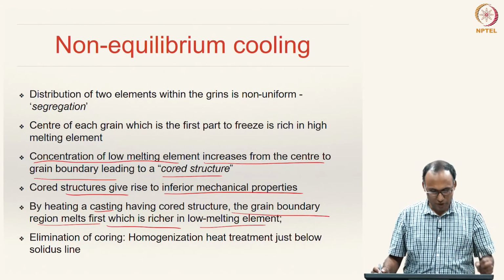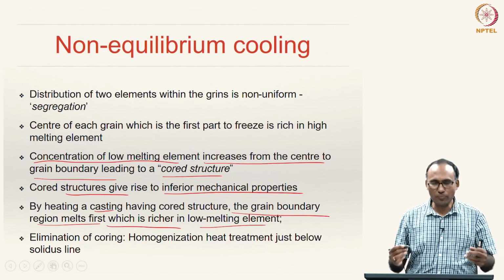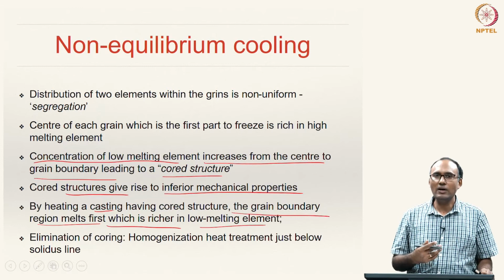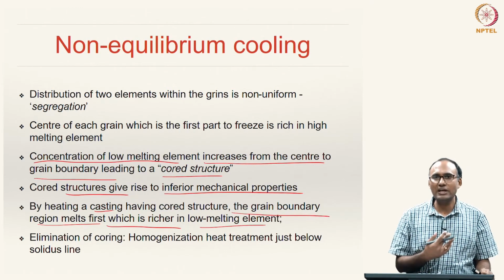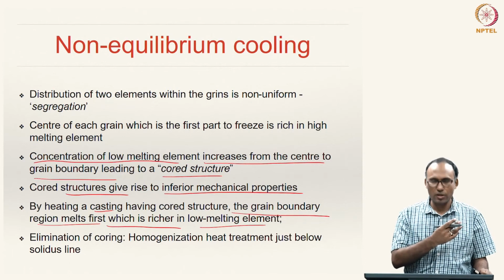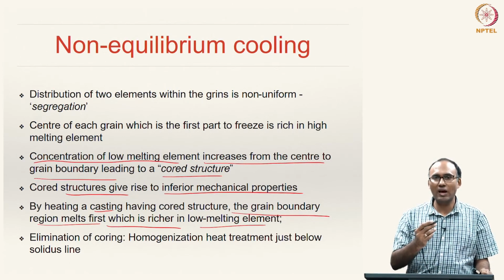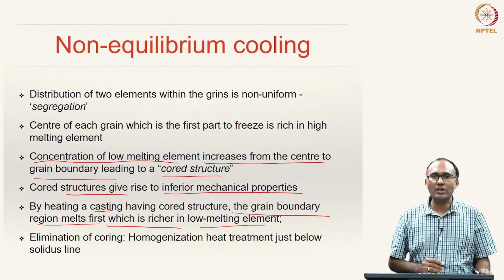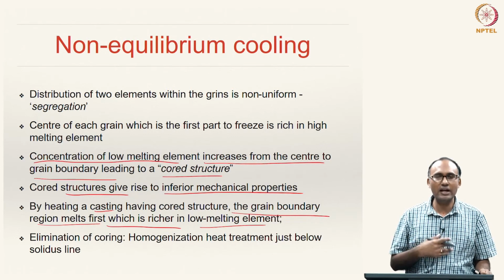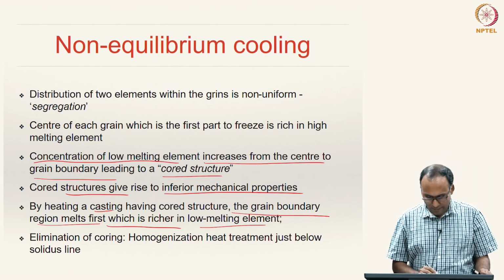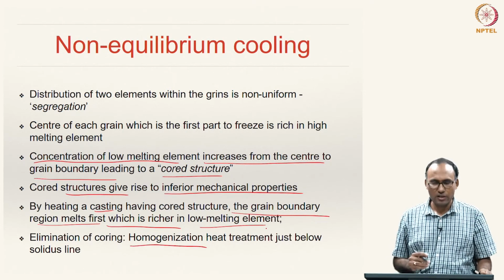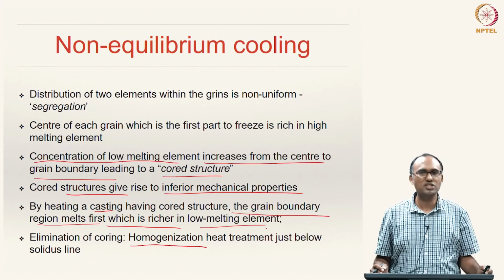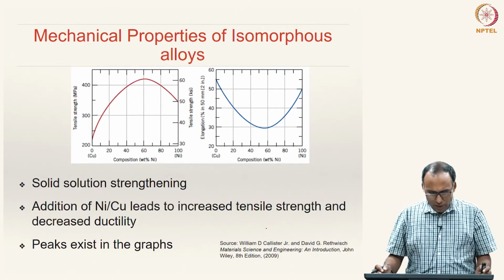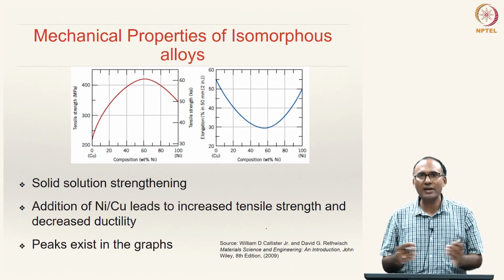actual service conditions. So, you need to do something about it, and so usually, however, in reality we cannot do equilibrium cooling. So, many times we will only do non-equilibrium cooling, but since we know that when we do non-equilibrium cooling we will have this kind of cored structures, you need to do something to eliminate this coring. So, typically at the end of the solidification process, all the alloys are usually subjected to certain kinds of heat treatments. Here you call this a homogenization type heat treatment, which has to be done in order to eliminate these core like structures.